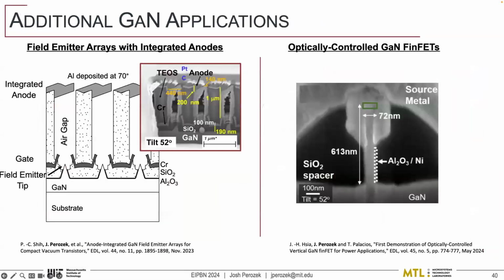And then while we're talking about this technology on the fabrication, it's also been used in our lab in a couple of other very interesting projects. One was some good work by Pauchon last year, where he was able to make the first integrated anodes on gallium nitride field emitters. So we were able to use that angle deposition to close off an air gap in a vacuum transistor. And then also some work by Sharon in using a very similar structure and modifying it slightly for optically controlled transistors.